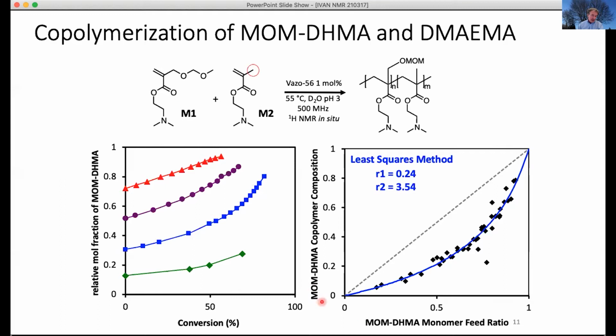And so we can analyze the data to figure out what's called the reactivity ratios, which is the propensity of monomers to react with another monomer of the same species or to cross-propagate. So it allows us to analyze and ultimately predict the composition of these systems.